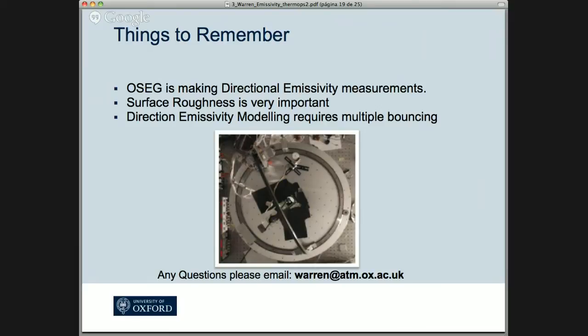Yeah, so I'm pretty sure the imaginary part of the refractive index is 0, because the Fresnel law gives a formula for the imaginary part of the refractive index, and if the electrical conductivity of the material you're looking at is 0, then the imaginary part will be 0, and the electrical conductivity of this paint is very, very small. And as for different refractive indexes across different wavelengths, you're right. It probably does change a bit. We need to start doing narrower wavelength filters and see. That's the best we can do.